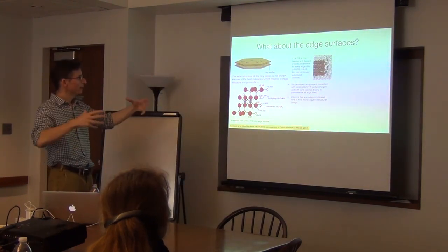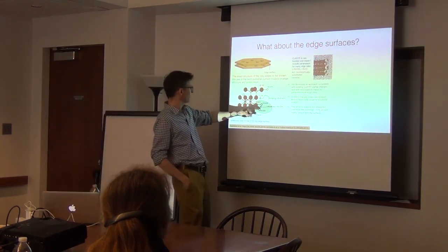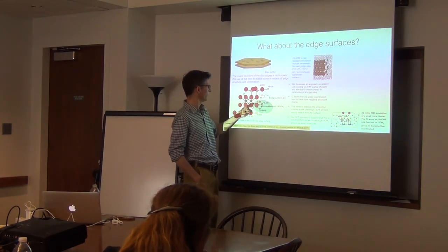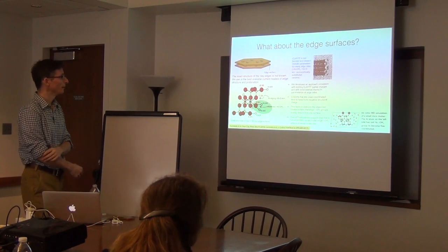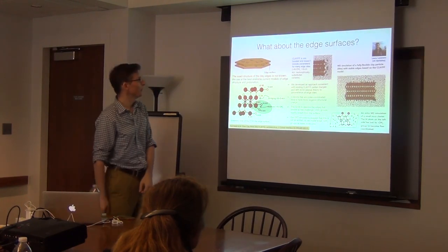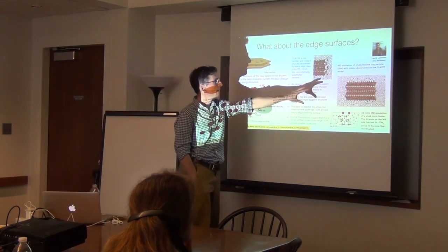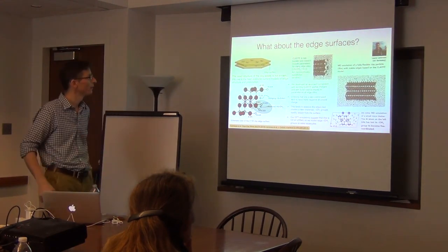We did ab initio MD simulations that show there's very little shared electron density in the middle of the O-Al bond, and frequently the OH2 group just detaches anyway, even with ab initio MD. So we turned this into a bare molecule and transferred the residual charge to the other atoms. Now we have a model where we can model flexible clay particles with cut edges completely surrounded by water. Laura Lammers, now a junior faculty at UC Berkeley, was instrumental in getting this to work — it was a joint effort.